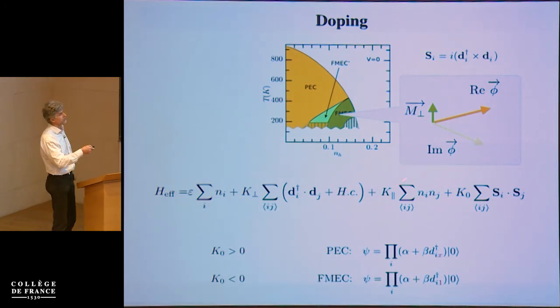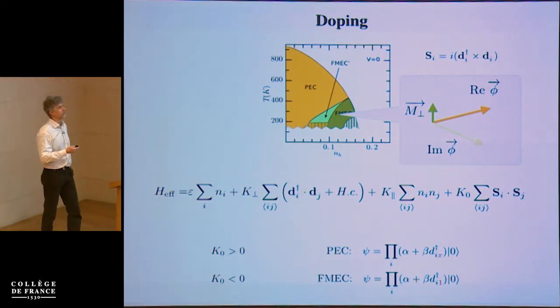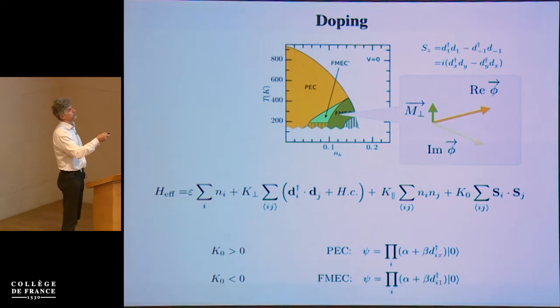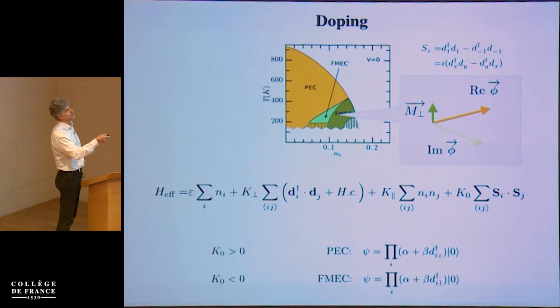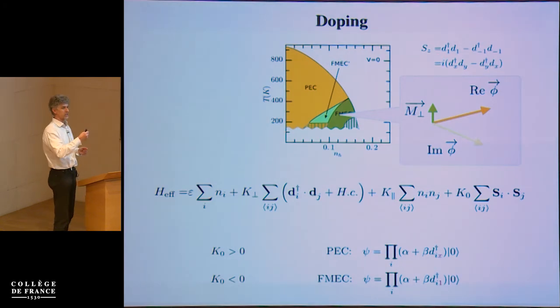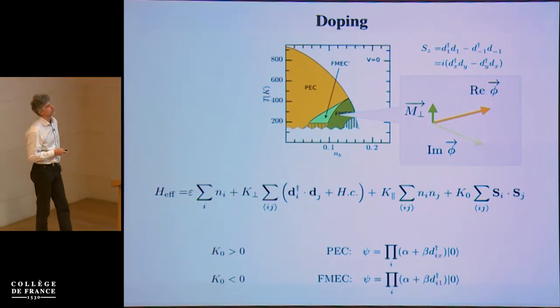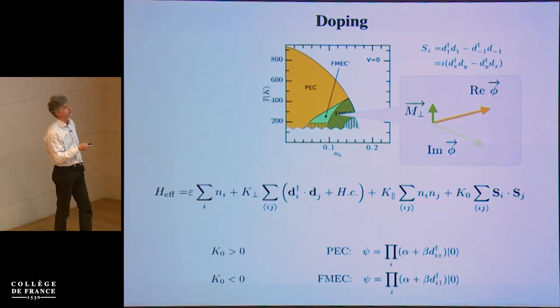It's actually rather simple to see why the angle between these two plays a role, because in the strong coupling picture, the local moment can be written in this form as a cross product of these two vectors. This is perhaps not a very intuitive way to write it, but if you decipher it, if you look at Sz, it's dx times dy minus dy times dx. If you go to the more familiar representation where Sz is the index, this is just equal to the number of bosons with Sz equal to 1 minus the number of bosons with Sz equal to minus 1. So this is a rather simple relationship.